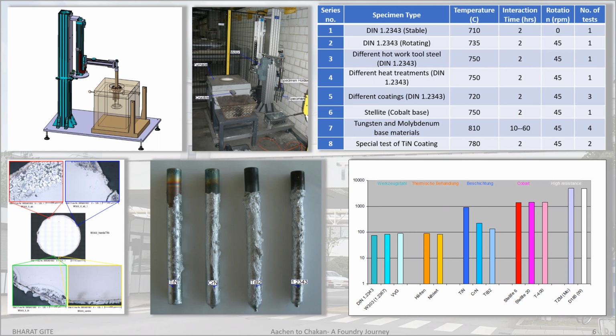contamination. The conclusion for these whole trials was: the higher the temperature, the more the dissolution of the DIN 1.2343 material in the melt above 750 degrees Celsius. I still remember the rotating DIN 1.2343 was totally dissolved when it was rotated. Molybdenum and tungsten are excellent erosion and corrosion resistant materials, but they are very expensive. Titanium nitride coating gave better wear and corrosion resistance against aluminum oxide, and its combination on a hardened DIN 1.2343 substrate is the best commercial choice.